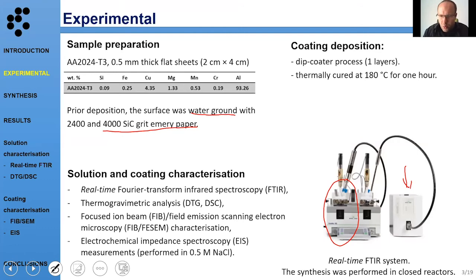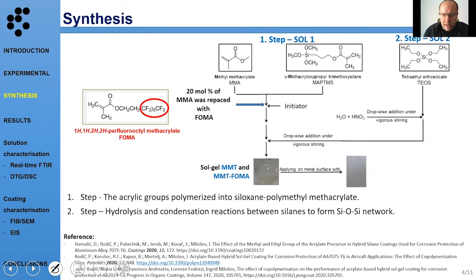After the preparation, we deposit these coatings with a dip coater, and we apply one layer of these coatings on the previously ground surface. After that, the coatings were cured at 180 degrees for 1 hour. Of course, we also perform some characterization, topography, and so on. We also measure thermogravimetric analysis and do some analysis with focused ion beam scanning electron microscopy, and we perform electrochemical impedance measurements, which were performed in 0.5 molar sodium chloride.